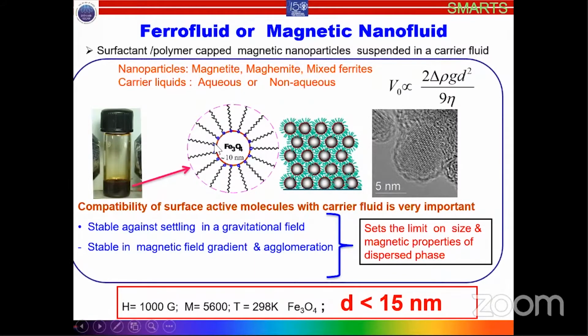It's not only particles. These particles are to be functionalized with a layer of surfactant molecules to prevent aggregation. The nanoparticles are highly reactive. You know that a lot of atoms reside at the surface, and as a result, they are very reactive. They have a tendency to aggregate. This is one of the problems you face when you synthesize nanoparticles: aggregation. If you want to prevent aggregation of nanoparticles, you have to provide a sort of sheath on the nanoparticles so that they may not be reactive, may not react, or may not come into contact.